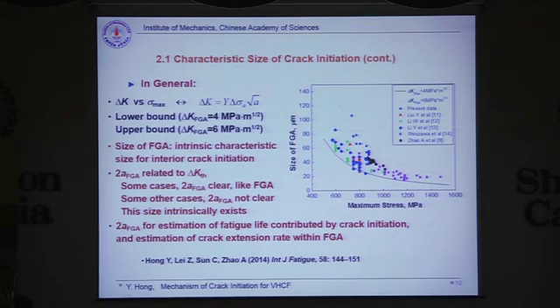Therefore, we say that the size of FGA is a kind of intrinsic dimension for crack initiation of very high cycle fatigue. This is our consideration. From this consideration, we are able to calculate the fatigue life consumed in this region during crack initiation, and we are also able to estimate the crack extension rate within this small range.